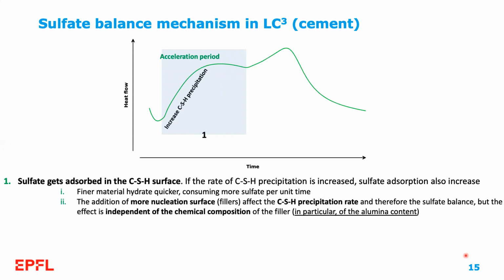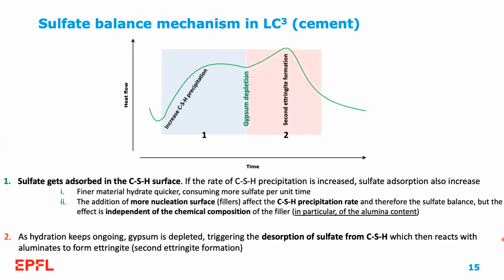And the addition of more nucleation surface, what we call fillers, which is basically what supplementary cementitious materials are doing, will affect the CSH precipitation rate and therefore the sulfate balance. But this contribution is in general independent of the chemical composition, as long as the chemical composition is not affecting significantly the filler capacity of the material. In particular, this is not directly related to the alumina content of the material. In the second stage, as the hydration keeps going, gypsum is depleted from the system, triggering the desorption of sulfate from CSH, which then reacts with the aluminates to form ettringite during the second ettringite formation, which we associate with our aluminate peak.